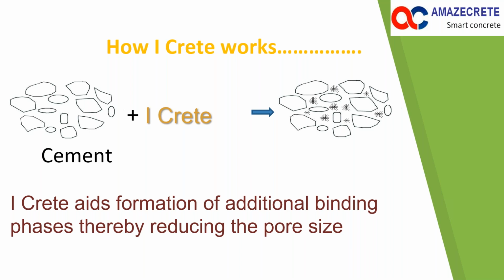iCrete, when additional binding phases are formed, fills up the capillary pores and then the pore size is reduced. So that is the important work of iCrete. In combination with the alumina and the iron present, it forms new binding phases other than calcium silicate hydrate gel and fills up the capillary pores, and hence makes the concrete denser, impermeable, and stronger.